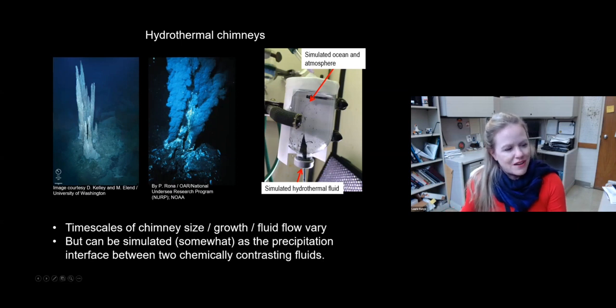So what we do is we have a vial, and we cut off the top of it here. And so the vial contains an early Earth simulated ocean. In this case, it's just a solution containing ferrous iron. And so there's iron dissolved in here. And then we purge the top with an atmosphere of nitrogen, so that way it stays anoxic. And then we slowly inject a hydrothermal fluid from the bottom. And in this case, the hydrothermal fluid has sulfide in it. And so then the precipitate that grows is an iron sulfide chimney.